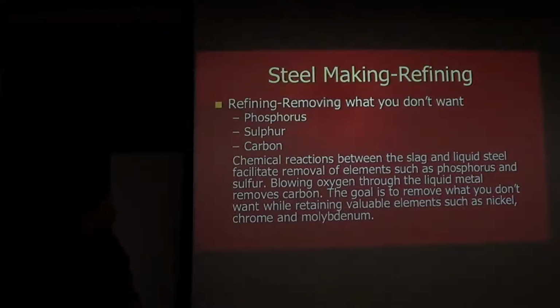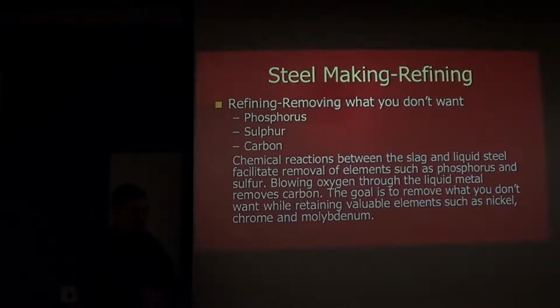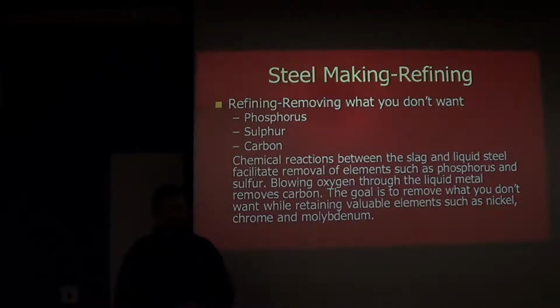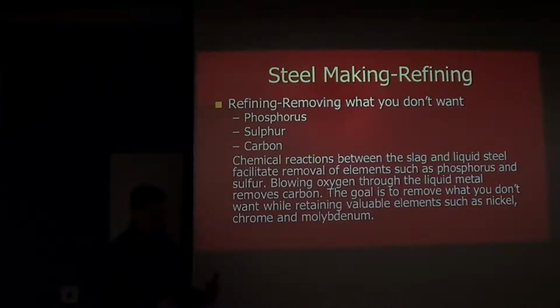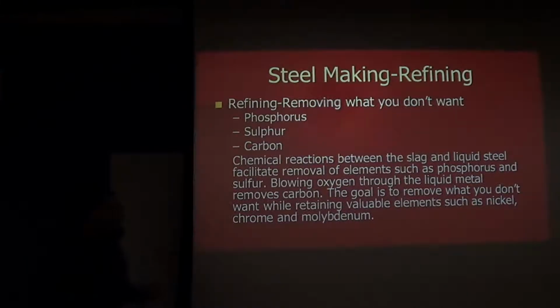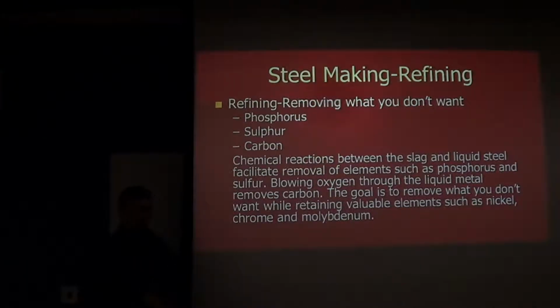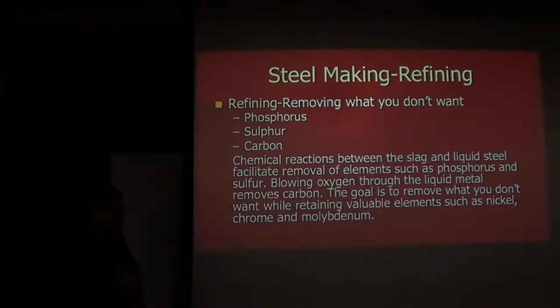They do that by having a chemically active material called slag, which tends to sit on the top of the bath of liquid metal, and then they'll use techniques to stir that liquid metal so that the slag and the steel can interact with one another. You can pull out the things that you don't want. Carbon is removed by blowing oxygen through there. Now, of course, one of the students here just asked about the pickup of carbon from the graphite electrodes, which is definitely a carbon source, so you may have more carbon than you want, so you're going to get rid of that by blowing oxygen through there.